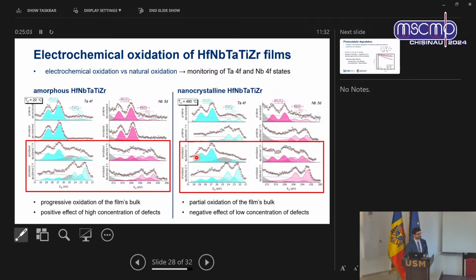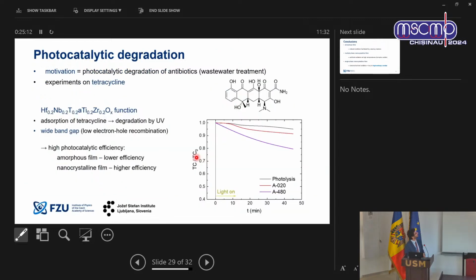And finally, this search for high entropy oxides is motivated by a nice application, which can be called photocatalytic degradation of antibiotics. It can be a procedure which you can use for wastewater treatment. And we did some first basic experiments on degradation of tetracycline. The function of this high entropy oxide should be that the tetracycline should be adsorbed on these high entropy oxides, and then we have more time and higher efficiency to degrade it by UV irradiation.